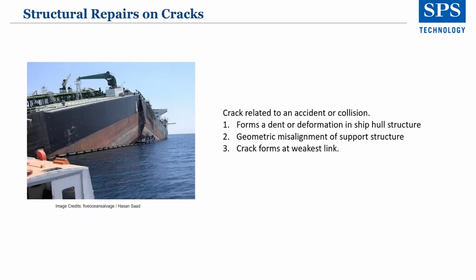Cracks are not easily detectable. They can go unnoticed during routine inspections, especially during the early period of a ship's life, when the perception is that the ship is brand new out of the box, so nothing should be wrong with it. But once a crack is formed, it spends almost 80% of its lifetime in the region of a short crack before it finally starts to propagate fast, leading to failure. Repair of cracks involves cost and time, and given a ship's charter commitments, it may not be possible to repair cracks on a priority basis once they're identified.